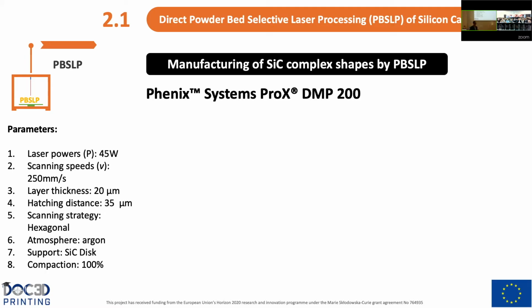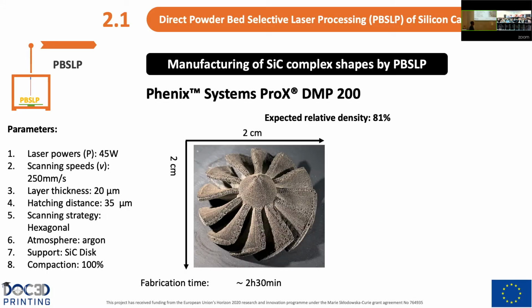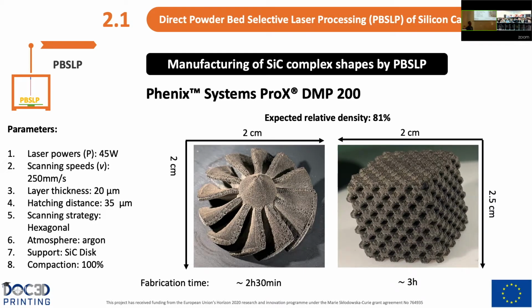So now we can assert the process viability of this optimization, because now we are able to manufacture complex shapes of silicon carbide. Specific specimens, with this dimension, had a fabrication time of 2 hours and 30 minutes. And we are able to manufacture as well lattice structures of silicon carbide that can only be manufactured with additive manufacturing methods and not with traditional manufacturing methods.